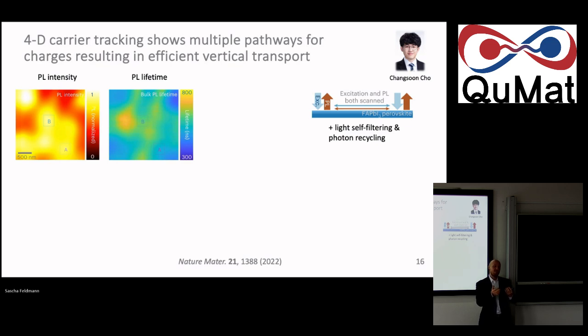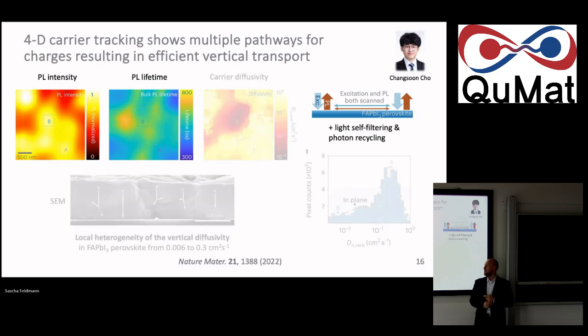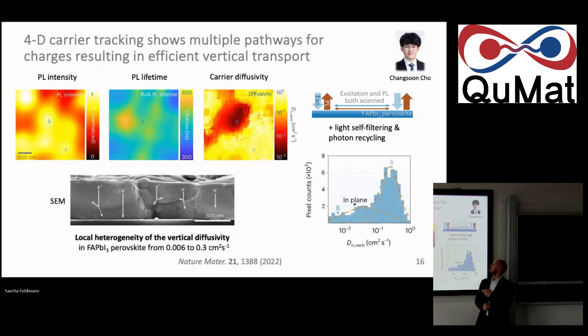It might have been reabsorbed halfway through. It might have then re-emitted a photon again. It might have been trapped, might have diffused further down. So from all these self-filtering and photon recycling phenomena that we can take into account using these different measurements, we can actually stitch together the full picture of how vertically the charge carriers must have moved through the system. So really, here you can now see a vertical carrier diffusivity map.